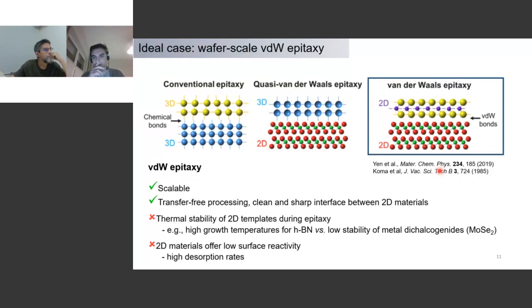And a second thing is that in van der Waals epitaxy, you would expect that ideally you have only van der Waals bonds between 2D materials. And the direct product of that is that when you start depositing by, for instance, MBE, the atoms that you need to grow your 2D material on top will immediately desorb, or they will have a very high desorption rate. That means growth will not be as effective as in the case of a conventional epitaxy, where you grow, for instance, a three-dimensional material on top of another three-dimensional one, where you have chemical bonds, strong bonding at the interface that favors the growth and so on. So there are many issues. This high desorption rate is one of them.